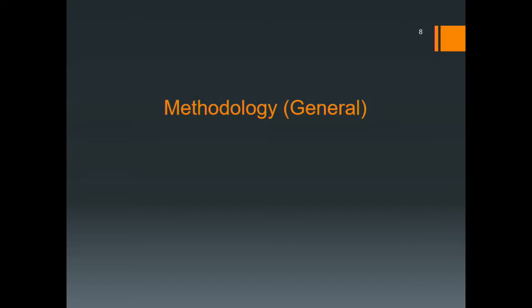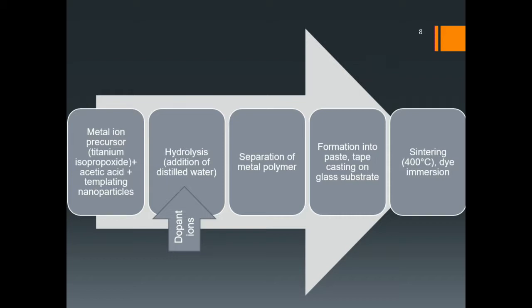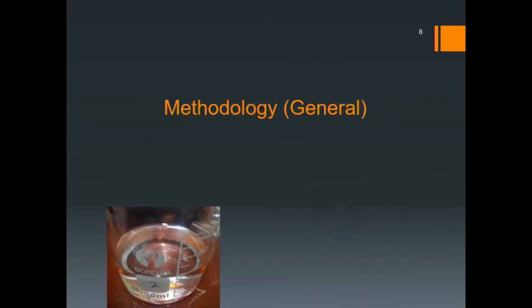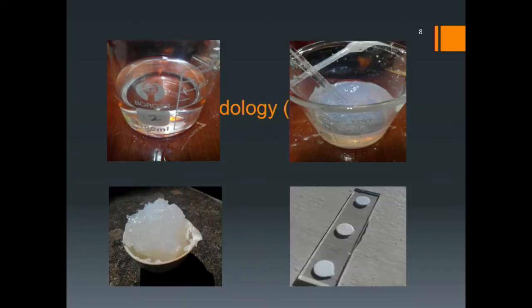So an overview of the methodology: we start with the metal ion precursor, which is titanium isopropoxide, and essentially add all the raw ingredients that are necessary to form these titanium dioxide nanoparticles with the right size and the right shape in an acidic medium. They undergo hydrolysis, and eventually at the end of this process, we get a white paste, which is heated at a high temperature and formed into the cells. So we start with a clear liquid, and at the end of the process, we end up with these white spheres, which can then be soaked in the dye and converted into our solar cells.